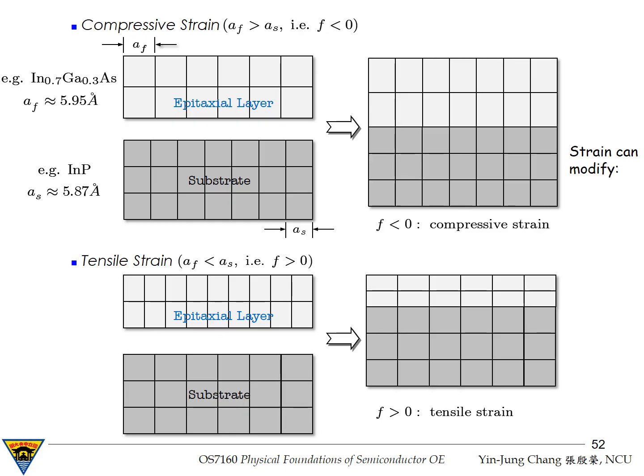Now that we understand pseudomorphic growth, let's look more closely at the types of strain that can occur in the epitaxial film. The type of strain depends on the relative lattice constants of the film and the substrate. Recall that we defined the lattice mismatch parameter as A sub s minus A sub f divided by A sub f, where A sub f is the lattice constant of the epitaxial film, while A sub s is the lattice constant of the substrate. Depending on the sign of this mismatch, the film can experience either compressive strain or tensile strain.